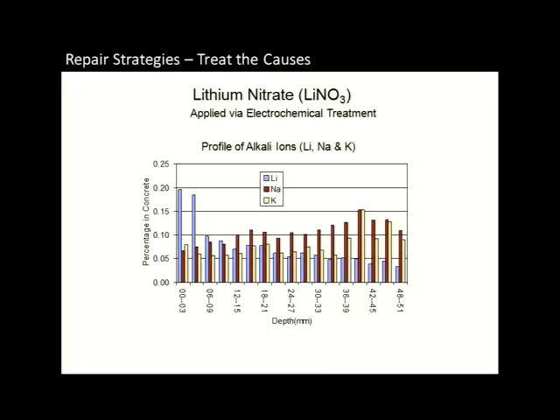We can get the lithium into the concrete very effectively and above the levels that we need to control the reaction. The problem, though, is that we're actually driving in sodium and potassium and concentrating them, especially right near the surface of the rebar, about 2 inches in. So we're actually setting up the propensity to have more severe reaction right at the surface of the rebar. So it was a very interesting finding.